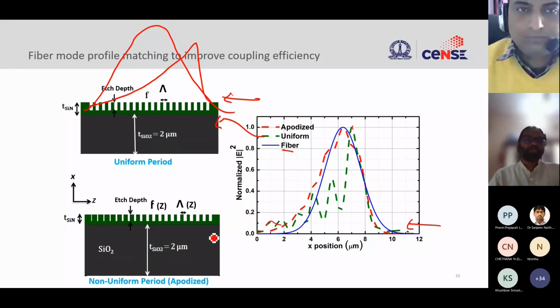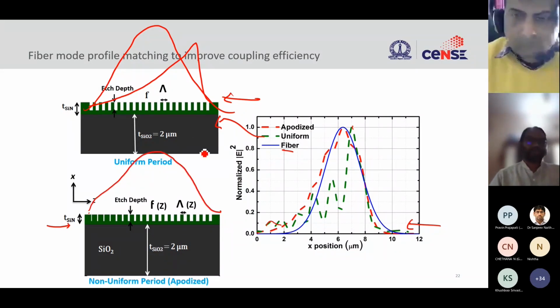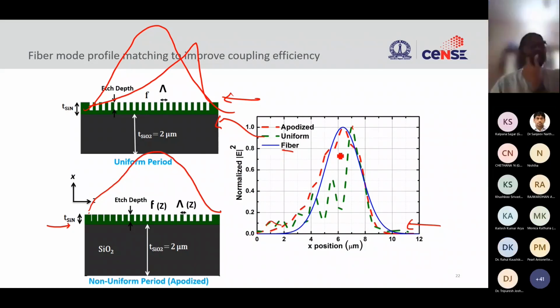So that's why what we use is an apodized grating. That means the strength of the grating is varied. So if the light is coming from the side, let's say, you will have very weak grating here and a strong grating here, and then it goes like this. Okay, and that is what you see in this red one, what we call apodized grating, right? Changing the strength of the grating along the propagation direction. And this matches very well with the fiber mode. And when you match these two, then you get better coupling. And that is from the shape itself, you can see. So it fits into that shape, right?